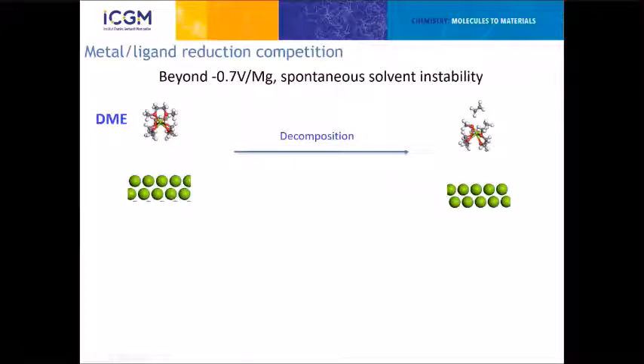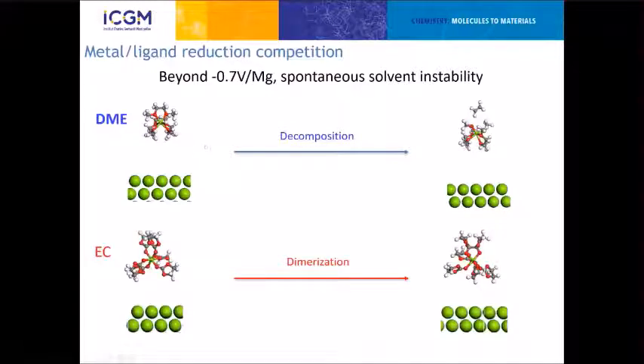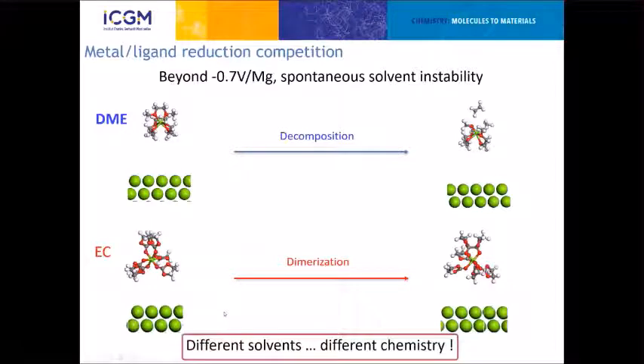For DME, we observe a spontaneous decomposition into ethylene and mostly methanolate, that's the magnesium dimethanolate, at this potential. So that would correspond to reduction not of the magnesium 2+, but of the solvent around. And for ethylene carbonate, we also observe spontaneous evolution, this time a dimerization. Two ethylene carbonate molecules just form a carbon-carbon bond with many other reorganizations in the geometry of the ring. So with these different solvents, we have very different chemistries. That could of course be somehow expected.